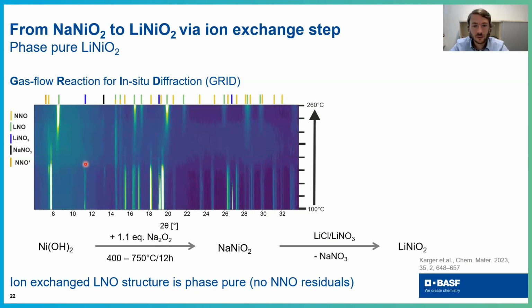And for sure, then at some point, somewhere below 200, I think 180, everything melts. Not everything, but your salts, lithium nitrate, melt. And you see that the sodium nickel oxide phase is disappearing, and then we see formation of our lithium nickel oxide, which is then finished at around 260 degrees.